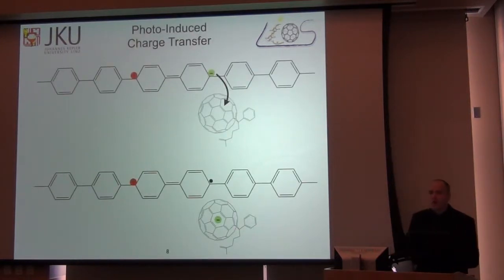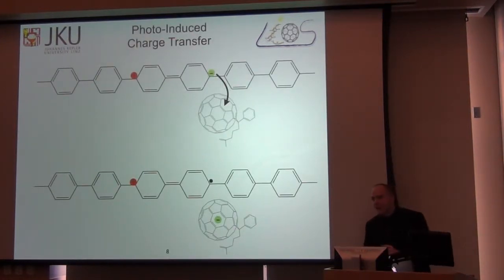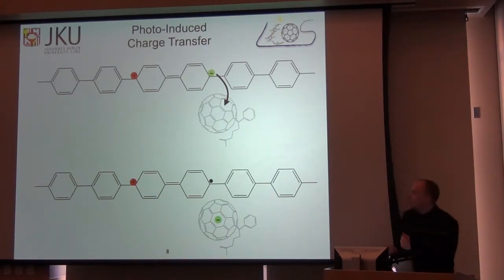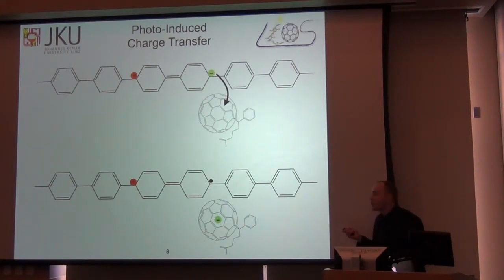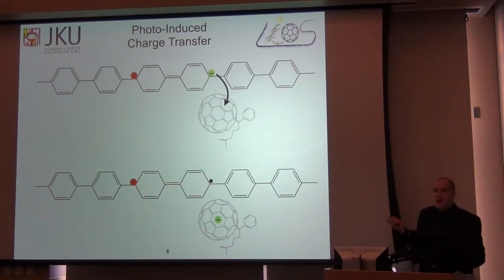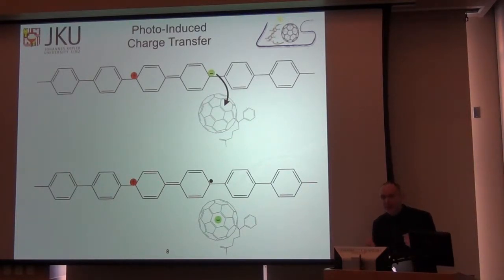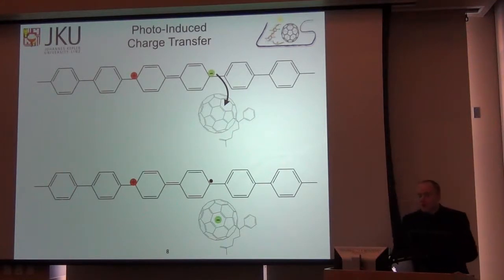So if we want to photo-induce useful charge carriers, we need to do what's called photo-induced charge transfer. We have an acceptor molecule, a separate organic semiconductor, and that's why I lumped polymers with fullerenes, because this C60 fullerene is the most commonly used acceptor molecule. So you photoexcite an exciton on the polymer, but if there's an acceptor molecule near to it, the electron can transfer to it, leaving behind a positive charge on the polymer and a negative charge in the fullerene. And these separated charges can then be used.